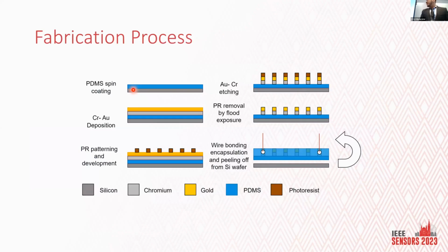So this is about the fabrication process. I fabricated this entire sensor using a semiconductor manufacturing process, which is more known for rigid substrates, but since we want to fabricate on a flexible substrate, we took a silicon wafer and deposited PDMS on top of this, in the usual 10:1 proportion. Then we deposited chrome and gold, did photolithography using some photoresist, etched the interdigits, and removed the PR using flood exposure.